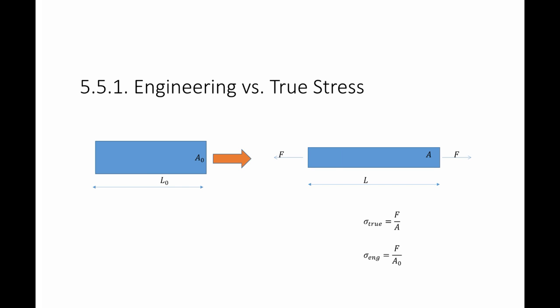However, depending on whether the area has been calculated as the force is being applied, it is common in material labs that the stress is calculated by dividing the force by the original area, F divided by A₀. This is termed the engineering stress.